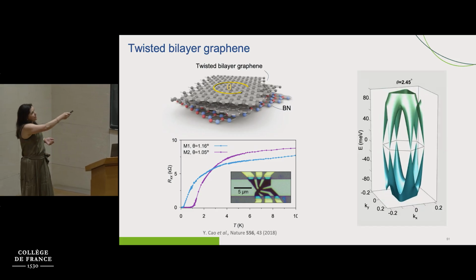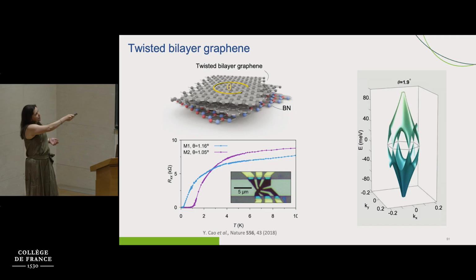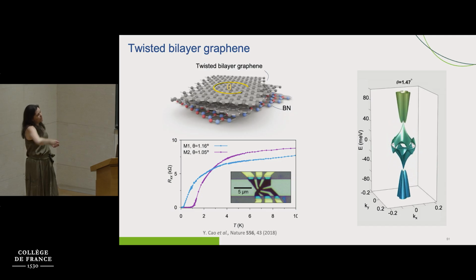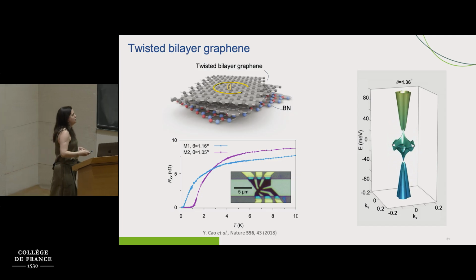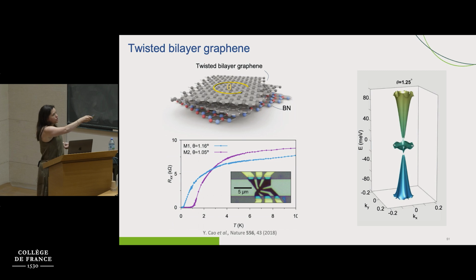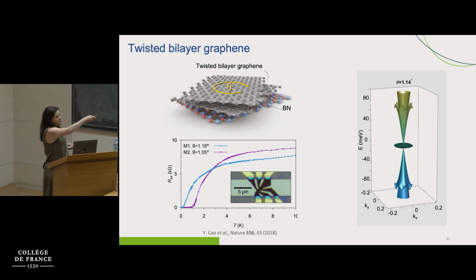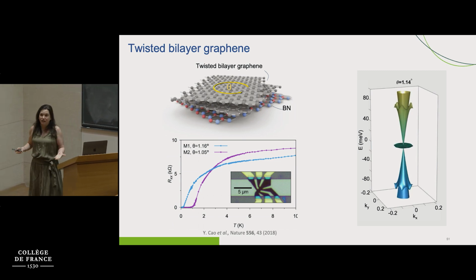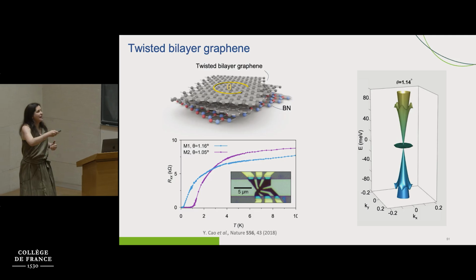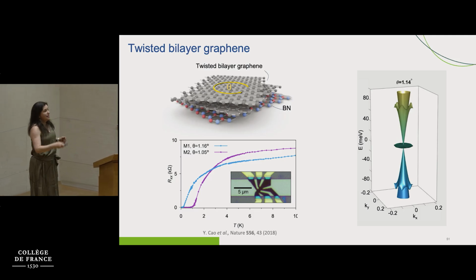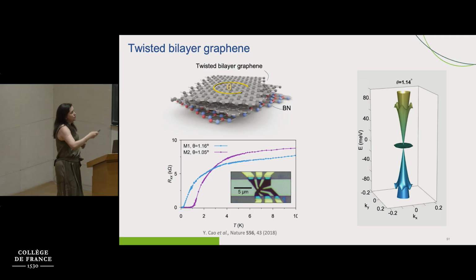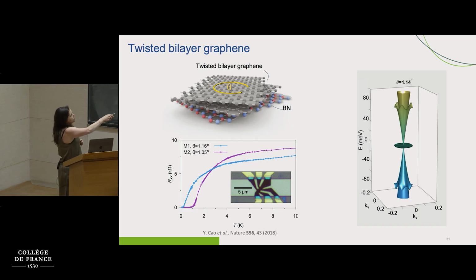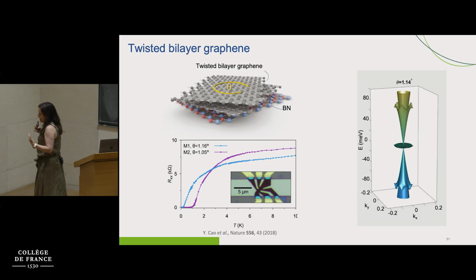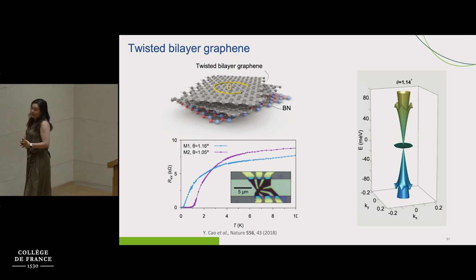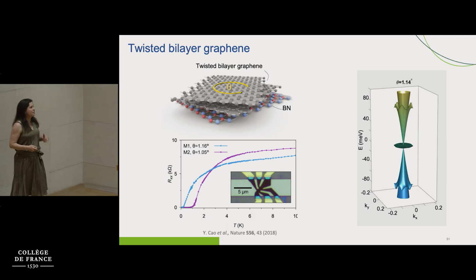So in fact, when we take 2 layers of graphene and change the angular alignment, as we can see in this numerical simulation, the electronic band structure is going to get modified, and at a certain angle called the magic angle, what we're going to have is a flat band, okay? This flat band is believed to be responsible for the observation of strongly correlated states, superconductivity, etc., in twisted bilayer graphene.